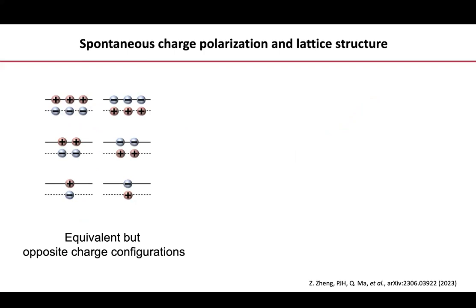You had already broken inversion symmetry because you had different rectangles at the top and at the bottom interface. Yes, but that's a symmetry-breaking field which does not do much other than aligning the excitons in the vertical direction. Because in a regular ferroelectric you go through inversion symmetry breaking, but the two ferroelectric states have the opposite polar axis. But I can go between this state with the electric dipole moment up and this state with the electric dipole moment down, but the angles don't rotate and it becomes the flipped structure. The angle remains the same.